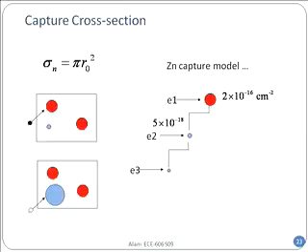On the other hand, let's say it has captured a certain number of electrons; for the hole it is very attractive because it is a charged thing, and therefore a hole can easily capture. So look at this number. As soon as it has captured an electron, for the second electron, E2, the cross section is small. It doesn't want a second electron, but it wants a hole.